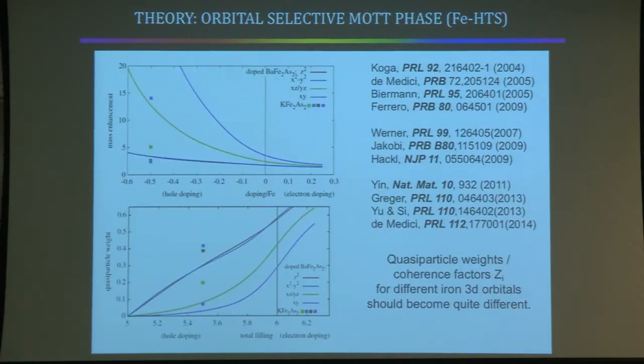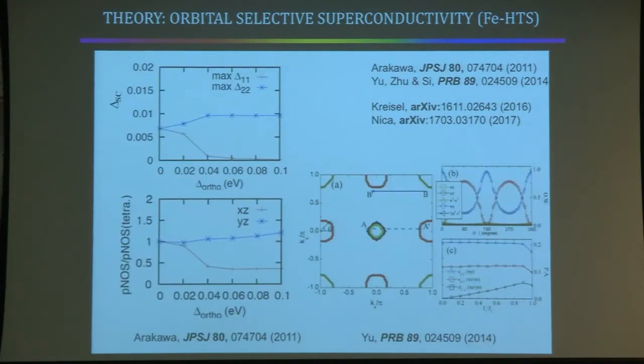If that happens, so suppose orbital selective Mott phases exist in nature, an immediate implication, which was realized only a couple of years ago, so let's say starting in 2011, is that you would get orbital selective superconductivity, because some orbitals would be coherent and have large enough spectral weight to form Cooper pairs. I mean, some quasiparticles with an orbital identity would be coherent enough and have large enough spectral weight, and others would not. So the prediction is that you should find orbital selective superconductivity if you have orbital selective Mott phases.